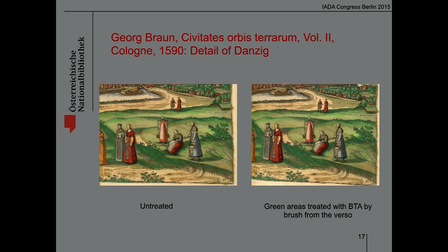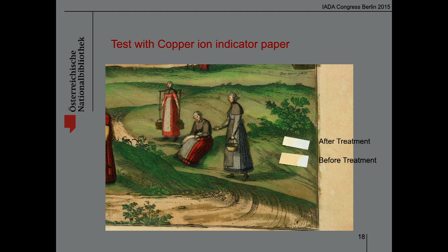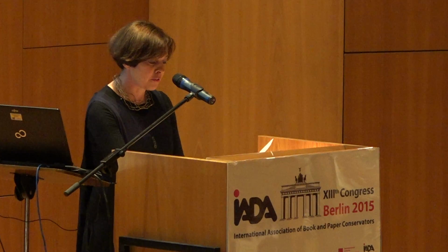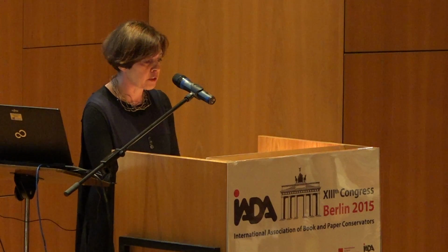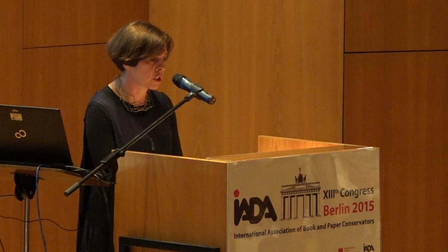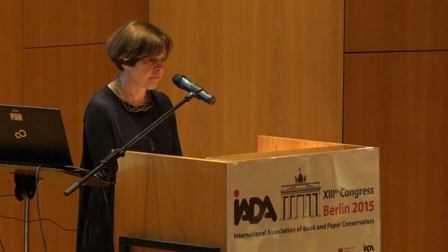The effect of complexing was monitored with copper ion indicator papers. In areas in which verdigris had discolored to brown, the indicator papers showed an orange reaction. Overall, there were orange spots. The application of BTA was judged sufficient when the copper indicator paper showed no or light orange reaction on the verso of verdigris.